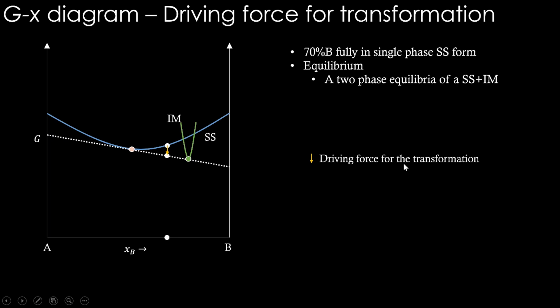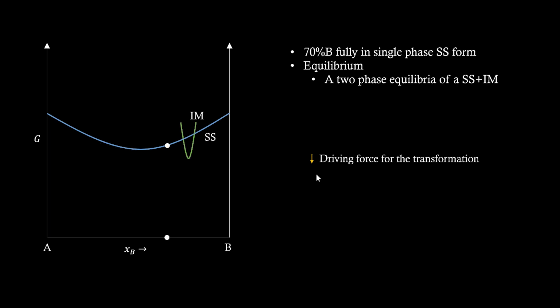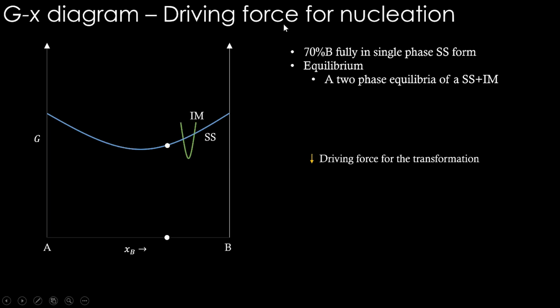So this is the driving force for the transformation, where the Gibbs energy of this metastable state and the Gibbs energy of the final state are taken, and the difference between them is calculated to be the driving force. It is different from the driving force for nucleation. We'll see what this is.